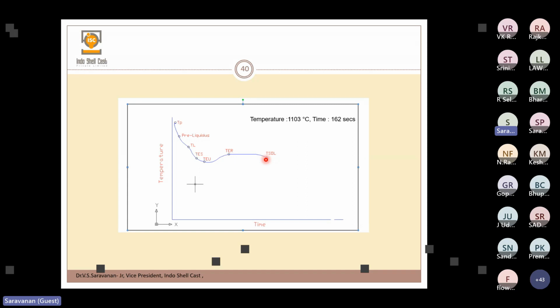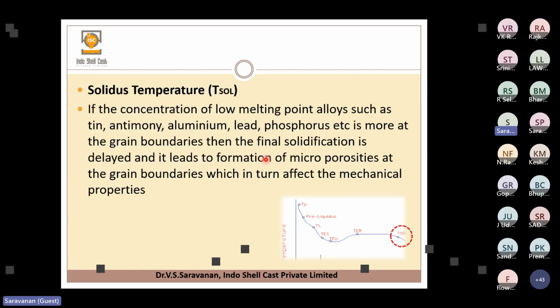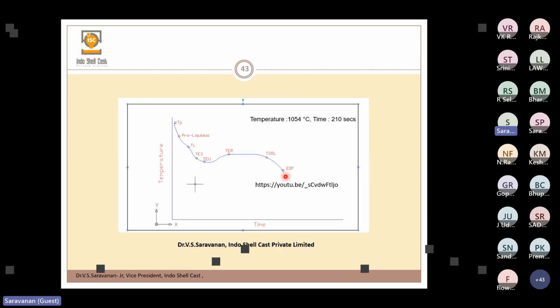That is why I told you this particular point shows the complete solidification of the iron metal, while some of the elements, the low melting alloys, are still in liquid form. Again, they will start solidifying further if the temperature goes down. Here, this is the end of freezing. At this point the complete metal, including iron and the other low melting alloys, becomes solid. So what is the temperature difference between T solidus and the end of freezing? If it is more, it says that we are adding more low melting alloys, like manganese, chromium, tin, copper, and so many things.